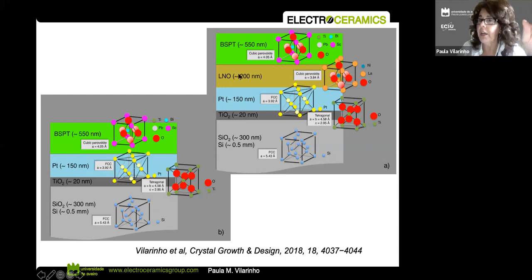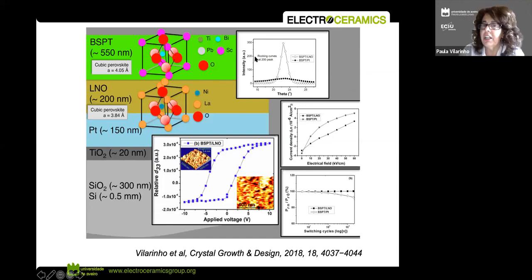But if I use a buffer layer, so again, I'm engineering the film by using a buffer layer that is an oxide, then the conversation between my oxide and my bottom electrode layer becomes easier. And that's exactly what I'm representing here. So I was able to orient my film according to the crystallographic orientation of this lanthanum nickelate oxide. And then by the end, the properties of this film are higher, including the ferroelectric hysteretic response, which in terms of aging becomes much better. And the hysteresis loop is very clearly represented here.